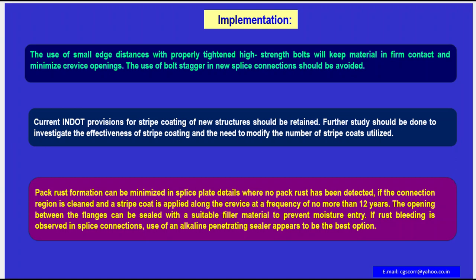Pack rust formation can be minimized in splice plate details where no pack rust has been detected, if the connection region is cleaned and stripe coat is applied along the crevice at a frequency of no more than 12 years. The opening between the flanges can be sealed with a suitable filler material to prevent moisture entry. If rust bleeding is observed in splice connections, use of an alkaline penetrating sealer appears to be the best option.